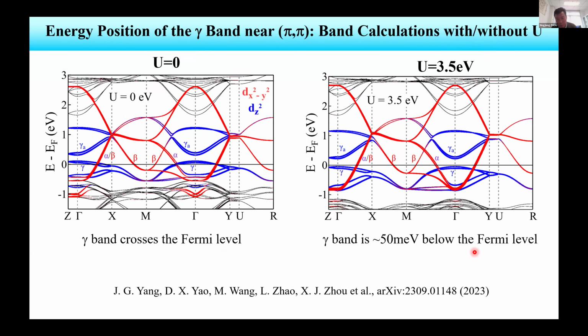Actually, we also performed some band structure calculations. From the calculation, we found that if you don't put U into the calculation, mainly the dz squared band crosses the Fermi level. But if you put some U, like in this case a U equal to 3.5 eV, this band goes below the Fermi level. So by putting some U, we can move the position of this dz squared derived flat band from above the Fermi level to below the Fermi level. And from our experiments, we found that this band is below the Fermi level, so we have to put some U in order to understand this behavior.